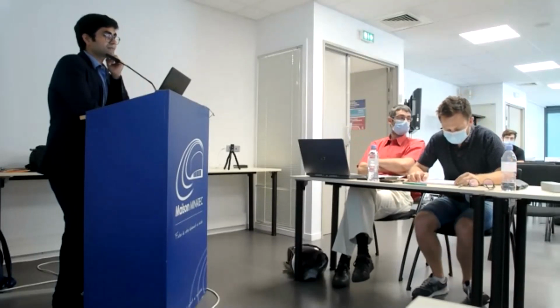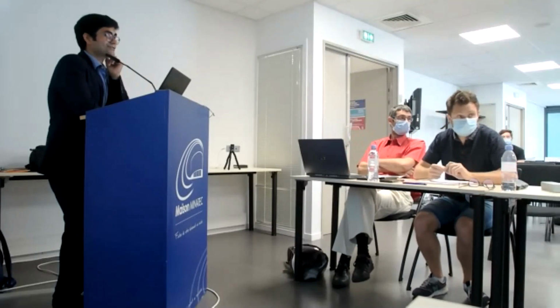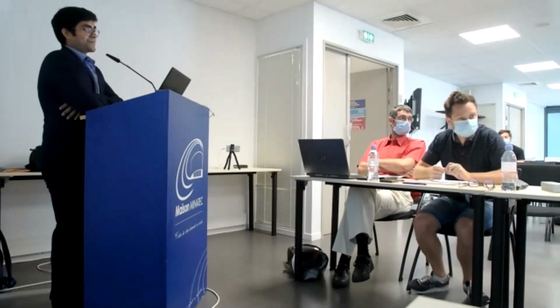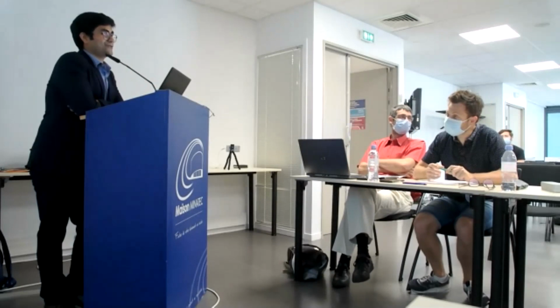And my last point is about your prediction of solid fraction versus temperature. Yes, it's based on Scheil-Gulliver. True. Do you think Scheil-Gulliver is applicable to such conditions? And what is the role of what happens in the liquid, the Marangoni flow and back diffusion in the liquid, and so on? And if you are remelting, what happens in the solid during the cooling down and reheating? All these parameters, do you think they may play a role?